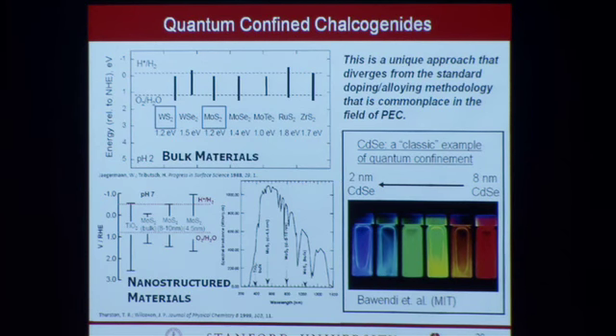And so really the dichalcogenides seemed particularly interesting to us. Here's a number of them listed. And you can see that the valence and the conduction band of these semiconductors, for the most part, are not that far apart. They're about 1.5 eV, so they're pretty narrow gap semiconductors, which is good. You don't want to start with a really tiny bandgap, otherwise you really have to make it a small particle to quantum confine it enough to reach the 1.23 volts. So these are right in about the right region.